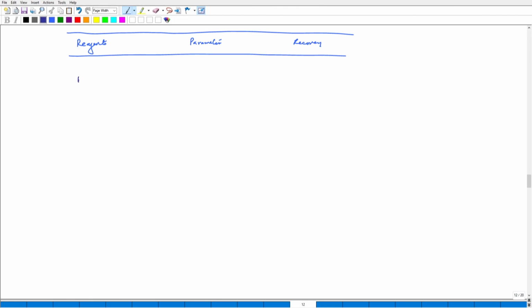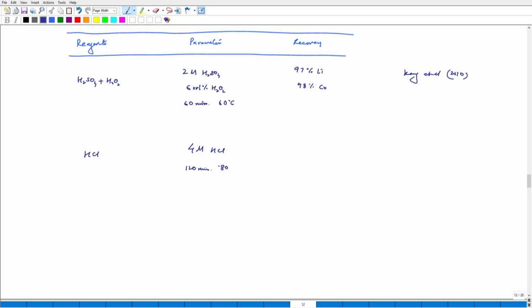So suppose that we use H2SO4 and H2O2. We have, let's say, 2 molar H2SO4, 6 volume percent H2O2 for 60 minutes and 60 degrees Celsius. We can have 97% lithium and 98% cobalt. And suppose we have HCl, we have 4 molar HCl, 120 minutes, 80 degrees Celsius. We can have, let's say, 97% lithium, 99% cobalt.